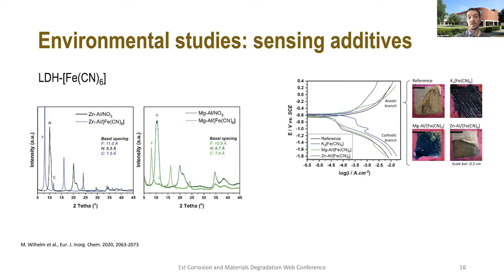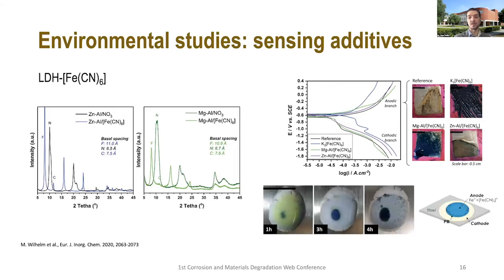And we could see this not only upon anodic polarization, but also when we used a kind of drop experiment where we had a sodium chloride solution with the LDH pigment dispersed. As you can see here, over time there is a yellowish color associated with the release of hexacyanoferrate in the presence of chlorides, and with time you see the formation of the blue precipitate in the middle, associated with the reaction of the iron with hexacyanoferrate.